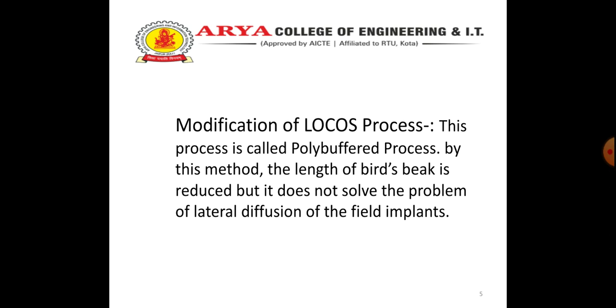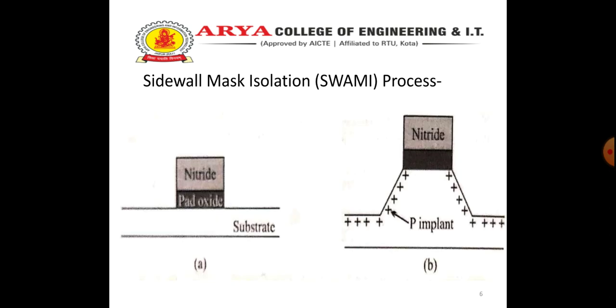Next is the modification of the LOCOS process, called the poly buffered process. By this method, the length of the bird's beak is reduced, but it does not solve the problem of lateral diffusion of the field implant. A sandwich of thermal oxide and polysilicon is extremely effective in reducing lateral encroachment and is quite popular. The polysilicon absorbs the effective stress resulting from the use of thin pad oxide and very thick nitride.